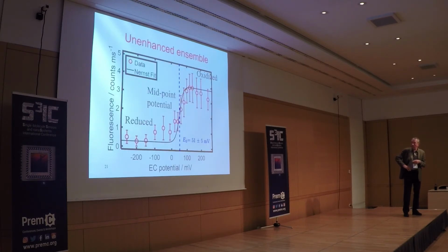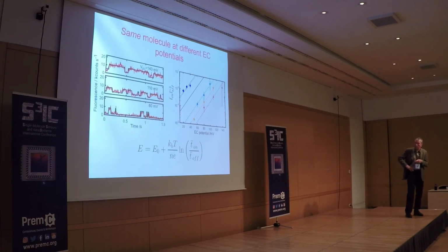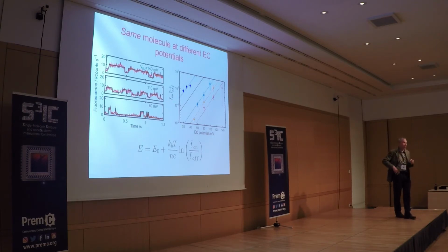And what you will find, as Anselmo mentioned, is essentially a trace like this, where you see here. Now, of course, it's not very convenient in our experiment to open and put some oxygen in and remove oxygen. This is too time-consuming. So instead, we just control the potential electrochemically. We make the environment oxidant or reductant according to the potential. We just apply a voltage, and in this way you can tune. By tuning the voltage, we can change the equilibrium between the oxidized and the reduced forms.